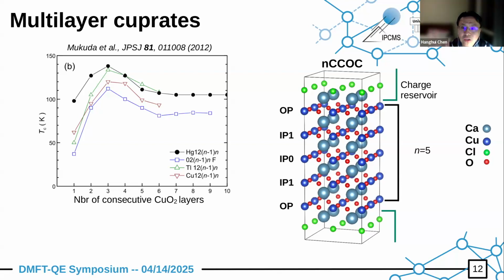Okay, thank you. I just want to give a quick comment from other communities. For example, we study the nickelate superconductors, and you also mentioned that in your talk. We have this bilayer nickelate, which becomes superconducting under high pressure. And it turns out that you must have two nickel layers in order to make it superconducting. If there is just one nickel layer, it is not superconducting. So it turns out that interlayer correlations seem to be important. And from your comment, it seems that in cuprates this is not the case. In cuprates, the interlayer correlations between the two copper-O2 planes probably play a less important role for superconductivity. I guess that is your comment, right?